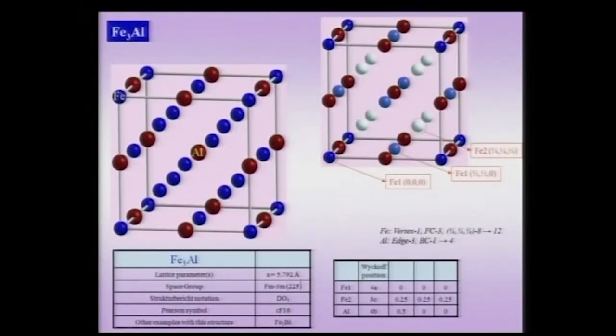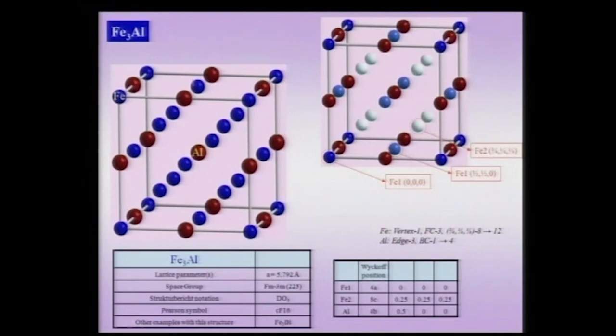How do I count the 16 atoms in this unit cell? Even though there are so many atoms, the lattice is still our face-centered cubic lattice. That means whatever atoms are present apart from the face-centering positions — you can see atoms in the face-centering positions shown as blue atoms — the other atoms have to form part of the motif. The iron atoms occupy the corners and also the face centers. I have also shown them as light blue colors. The dark blue and light blue colored atoms are iron, and we shall see they are actually in some sense different kinds of ions.